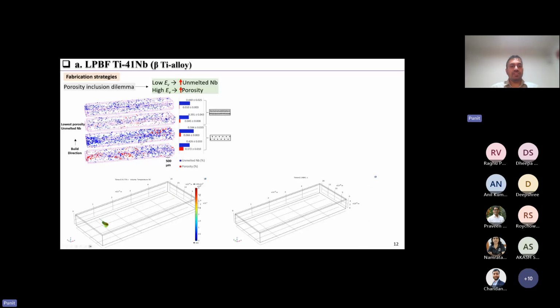There is one challenge that comes with that: titanium has a significantly lower melting point compared to niobium. So to melt all the niobium, you have to apply a much higher volumetric energy density inside the material, and when you do that, you might end up with an unstable melt pool, which leads to formation of keyhole pores. And if you try to reduce the volumetric energy density, you might have a lot of unmelted niobium particles, as you can see here. So there is a porosity and inclusion dilemma that you are dealing with.